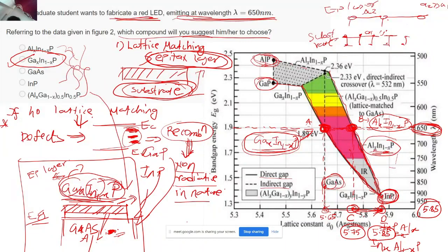So that's why I told him to let's move to point number A. So from indium phosphide we move to point number A. Now I projected point A's coordinate and I got the x coordinate over here. It was around 5.65. Now what are the substrates available to me? They are gallium arsenide and indium phosphide. Now just look at the gallium arsenide. Gallium arsenide is present over here. Okay. So if I project its x coordinate, it is exactly matching with the x coordinate of this point, right?